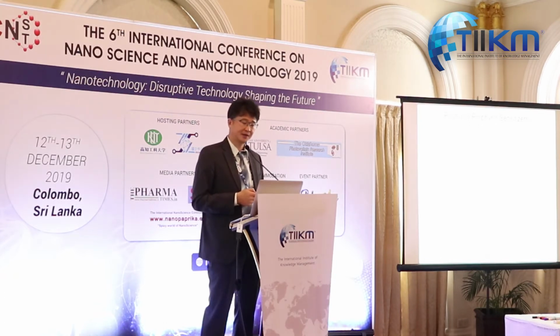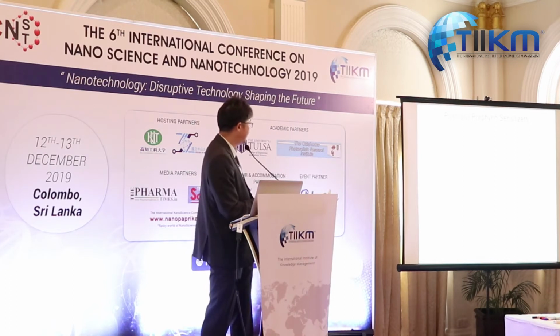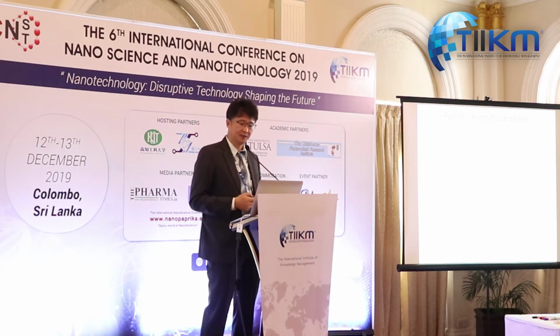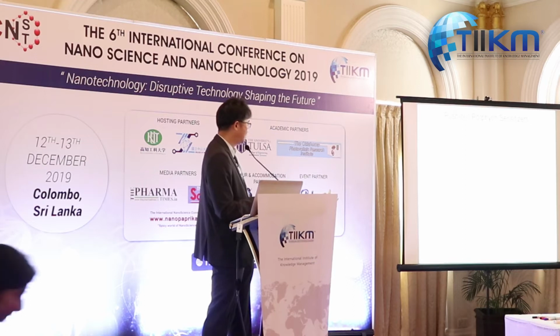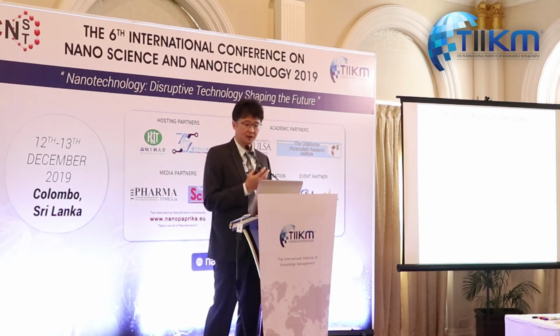we designed and synthesized the second generation of porphyrin dyes. In YD2, hexyl groups were used instead of tert-butyl to reduce molecular aggregation. And to increase the electron donating ability, alkoxyl groups were used for YD3 and YD4. And the electron donating effects are even stronger for this triarylamine. And YD6 to YD8 with triphenylamine were also prepared for comparison.